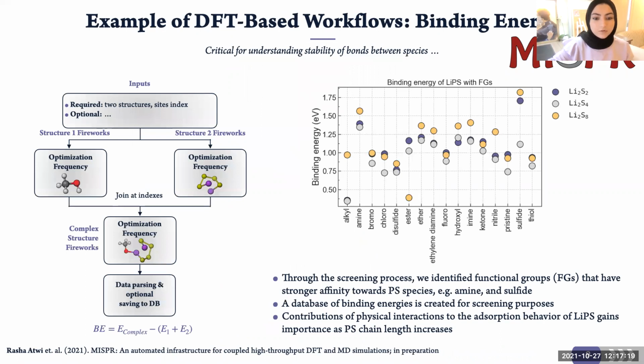Another example of a DFT workflow is the binding energy calculation, which is critical for understanding the stability of bonds between species. In a lithium-sulfur project, for example, it allows us to know whether a specific type of solvent has more affinity towards coordinating with the salt or with the polysulfide species in the electrolyte compared to others.